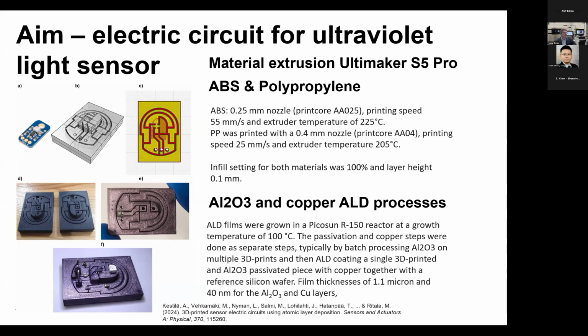Then we used aluminum oxide in the ALD process first. The problem there is that we cannot go much over 100 degrees, because then the shapes start deforming and it doesn't work. Many ALD processes require higher temperatures, so that was one challenge. But there are processes which use only 100 Celsius for copper, using water. That was a combination of different knowledge.